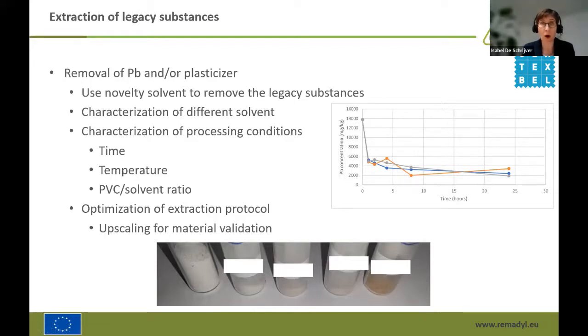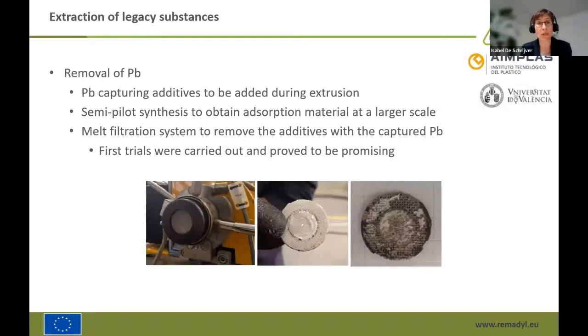So we ended up with a few solvents that were very useful to extract the lead out of the PVC matrix. So now we are at the upscaling phase, where we are trying to process some kilogram scales so that we can also fully re-evaluate the polymer properties after the extraction of the lead.